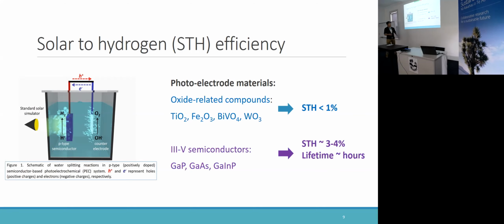For the III-V semiconductors, if we only use the material itself, without any tandem configuration or something like that, the STH efficiency can be 3 to 4%. So it's much higher than the first one. But the lifetime is only hours, for example 20 hours, 10 hours, or something like that, which means that we need to use new material systems to develop the PEC system.